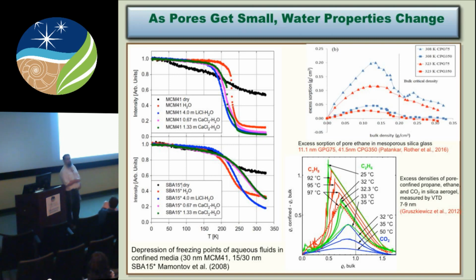This is a quasi-elastic neutron scattering spectrum for water, or in this case also water with lithium chloride in it, as a function of temperature. So here's about 200 degrees, for water confined in MCM41, which is a synthetic zeolite. And what you see is, this is the height of the elastic spectrum. So the lower this is, the more quasi-elastic scattering is present.